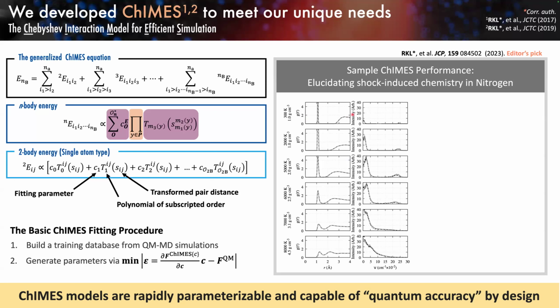As I go across a given row, this is data for a given state point. And so we go from nominally ambient conditions to 8,000 Kelvin and what turns out to be roughly 200 gigapascals. This first column, these are radial pair distribution functions. So they tell us about system structure. And in this column over here, these are vibrational power spectra, which tell us about the vibrational modes in our system. And the point here is that there are two sets of data in each plot. There is gray data, that is our first principles reference data, and then the black dashed data is our ChIMES prediction. And you probably can't tell that there's two data sets there because they're right on top of each other. So that's what we mean when we say quantum accurate.